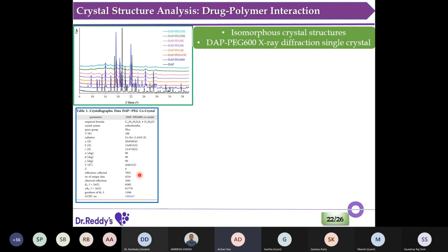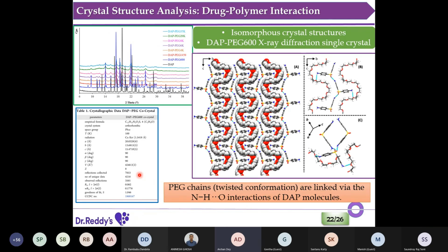So it's 4:1 PEG monomer versus 1 Dapson, and the crystal structure looks like this. In general PEG has a 7:2 helical structure, but here you can see it has a twisted conformation, and only the Dapson molecule is inserted. All the hydrogen bonding interactions that were assigned in the IR are present here. That gives real strength to what we understood: these strong N-H...O interactions are the only connecting part between Dapson and PEG.